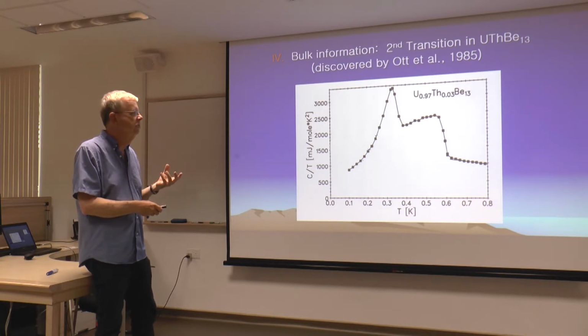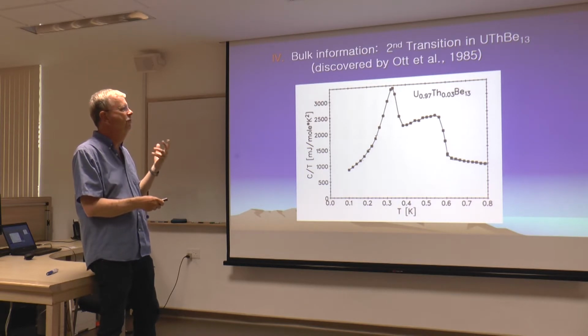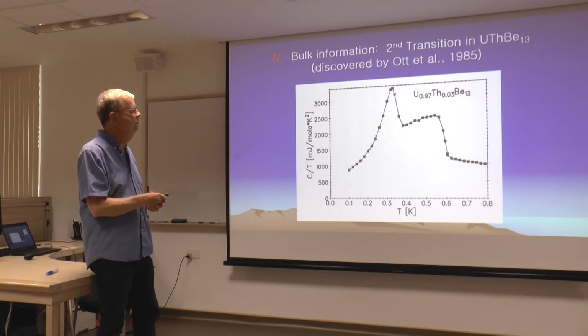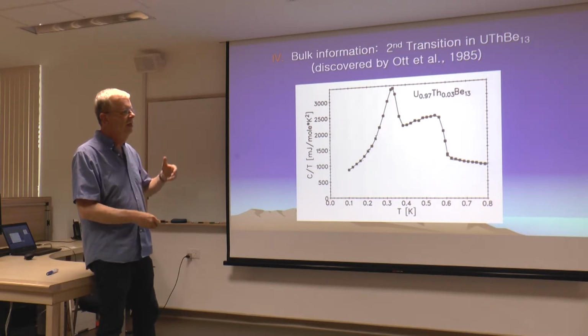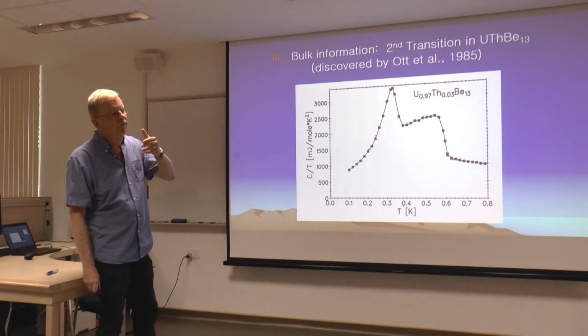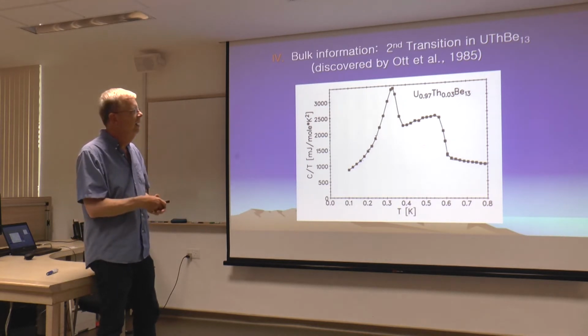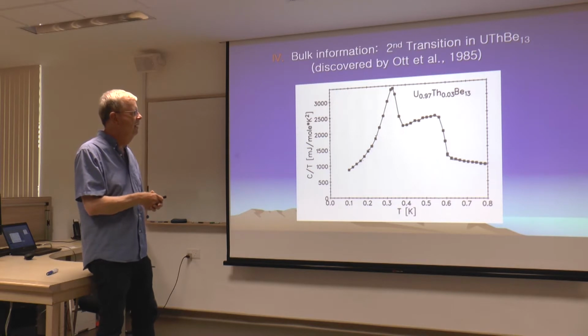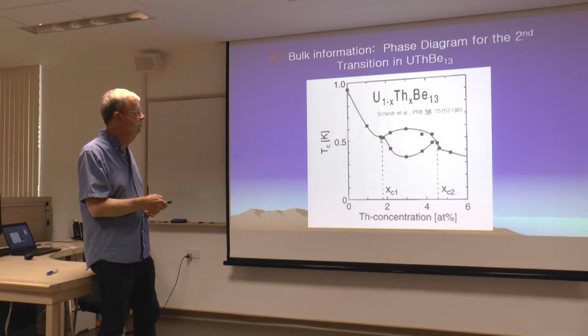It's a jump. It's just like the original cerium copper 2 silicon 2, and the referees said, well, you've got a jump, but how do we know that's a superconductor? The shielding has already taken place. But what you can do is look at the field at which flux first enters. You can look at HC1 as you lower the temperature, and the slope of the rise of HC1 with temperature changes here, implying a change in the superconducting density of states. So you can actually prove this is a superconductor, and there are, of course, other measurements, but that was the first one. So this is a very interesting phase diagram.